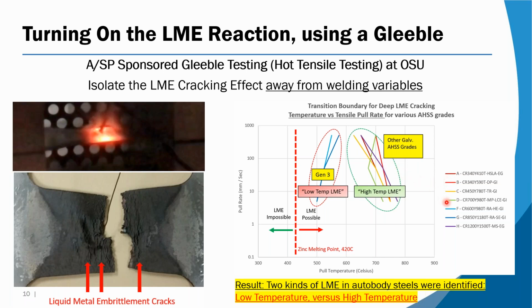Most of these body materials fell in this same general temperature range of 650 to 750 or so centigrade. Then comes along the Gen 3 materials, and they're cracking 500 to less than 600. The slope of these lines in the Gen 3 is backwards. You would think that if you pulled the sample at a slower rate, you might stave off LME and it might happen at an even higher temperature than low.